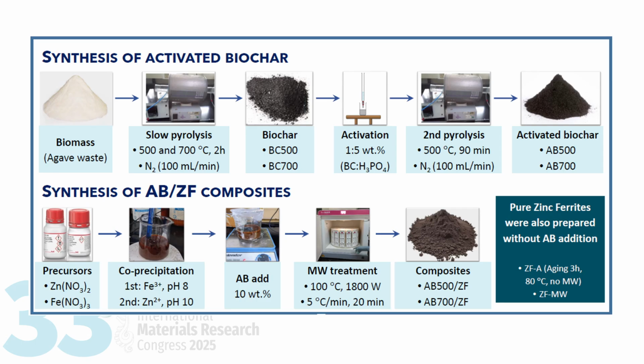Synthesis of materials. Activated biochar was obtained by a slow pyrolysis of agave waste at temperatures of 500 and 700 degrees C. Then, it was activated with phosphoric acid, followed by a second pyrolysis at 500 degrees C. The AB/ZF composites were synthesized by coprecipitation methods with an iron-zinc ratio of 2:1. First, iron was precipitated at pH 8 and then zinc at pH 10. Activated biochar was then added, followed by microwave treatment, obtaining the AB500/ZF and AB700/ZF composites. Pure zinc ferrites were also prepared without AB addition.